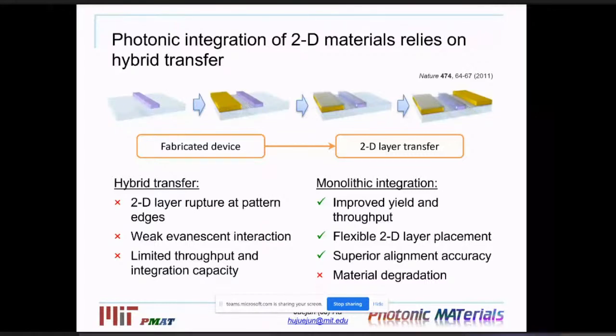This would then be compatible with high volume photonic manufacturing, and it also enables flexible configuration of the devices as well as superior alignment accuracy that allows us to leverage photolithography methods to align the 2D structures with the photonic circuit on top. So despite all these benefits, the monolithic process was not demonstrated because of one big issue. These 2D crystals turn out to be pretty fragile. If you try to deposit any kind of dielectric material on top, they tend to degrade, simply resulting from the deposition process.